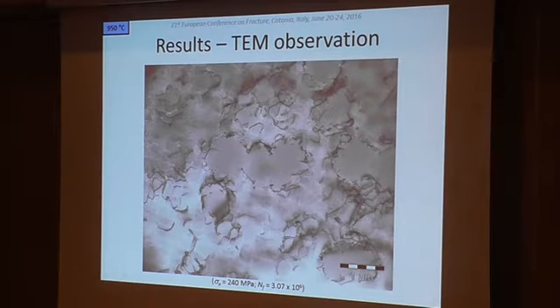And at the highest temperature, 950 centigrades, we had an almost homogeneous dislocation structure, which tends to show us that dislocations were already well mobile, so they were able to avoid the precipitates and were not restricted just to slip planes. Therefore, we observe a typical stage 2 fracture surface with fish eyes and striations like in normal metallic materials.